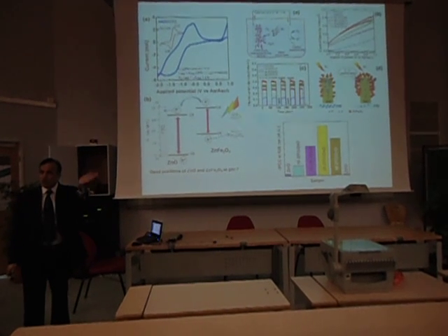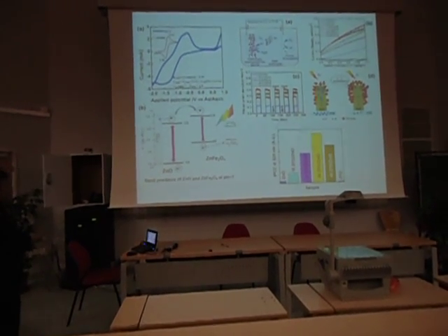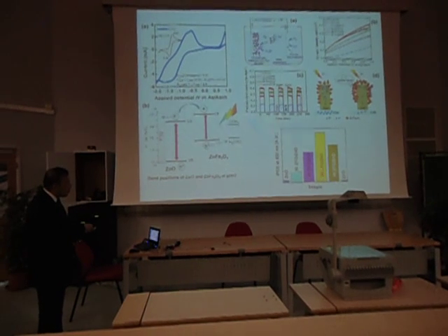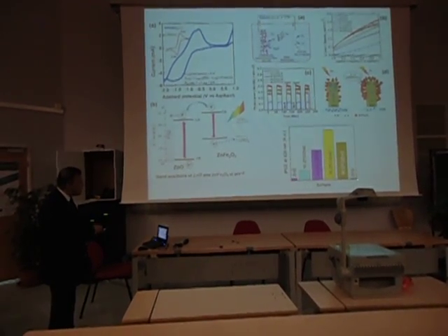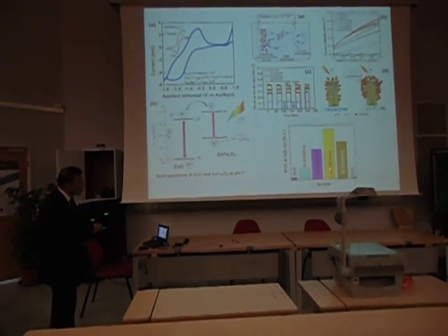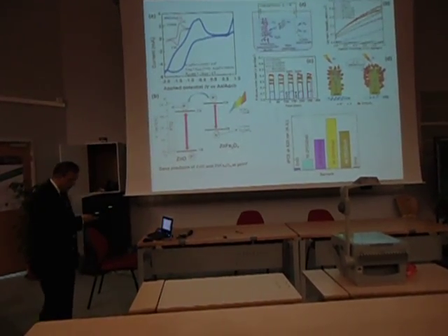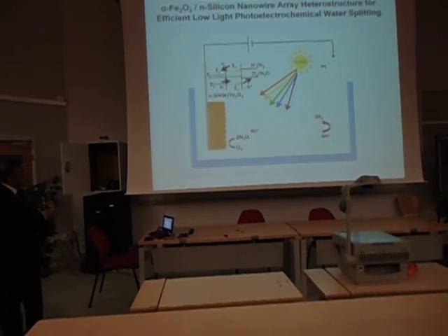So you use heterostructures where you try to use the positive properties of two materials and put them together into this particular device application. And what we have found here is that when you do a particular combination, this is zinc oxide performance, this is ZnFe2O4 performance, but when you make a heterostructure, the performance is dramatically high because of this charge separation and efficiency issues in terms of photoelectrochemical effectiveness. I will also give you another example.